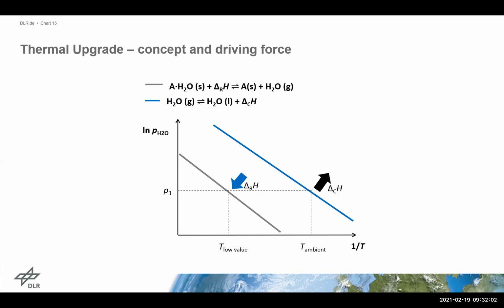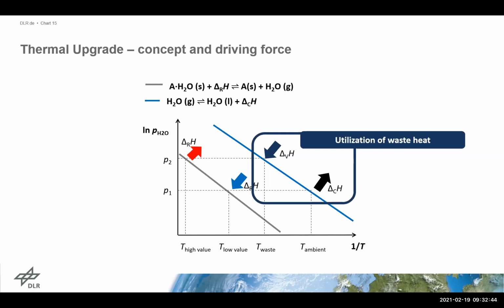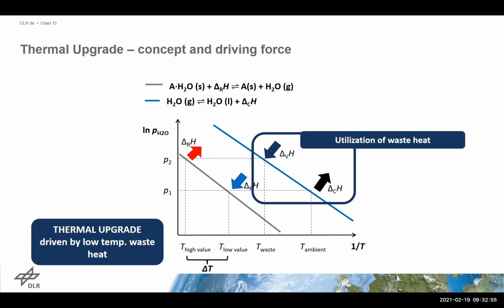At this temperature, we charge our solid material, dissociate it, generate water vapor, and then of course we do not want to increase the pressure, we want to maintain the same pressure, so we have to condense it in a second unit which is connected to it, and of course the heat of condensation we have to release to the ambient, or to higher temperatures, roughly 100 millibar as absolute water vapor pressure if we want to reduce it to the ambient. And if we say now, yes, okay, we have some waste heat, 60, 80, 100 degrees Celsius available, we can evaporate water, have a higher pressure, and then have a higher reaction temperature in our solid material. So in this case, we would try to utilize waste heat, not as heat in order to reintegrate it, but as driving force for our internal chemical heat pump, which we call thermal upgrade.